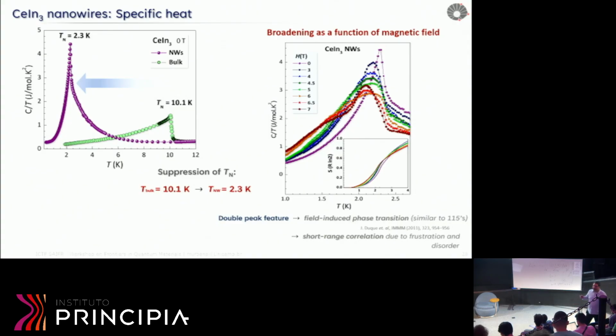These are macroscopic characterization of this system, but our entropy gives us some clue about what is going on with these interactions. I don't see the shade that I put there, but if you analyze the entropy at the transition, we can see that it's not recovering the full entropy here for the doublet. It's halfway, it's only 0.5, indicating a very strong suppression of the crystal field.